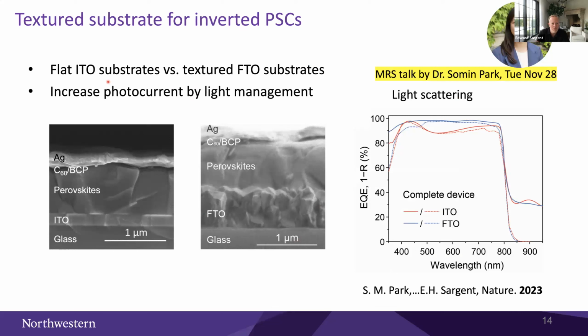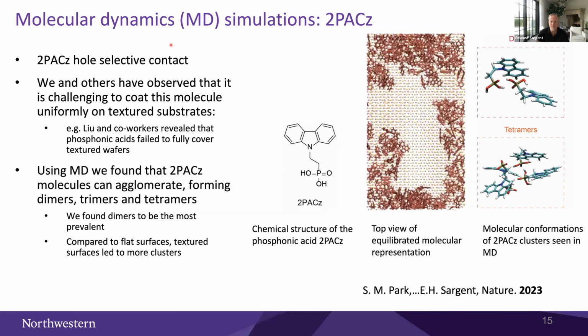the topic that Somin and her colleagues focused in on in particular was the question of whether we could integrate good perovskite active layers with textured FTO. The idea of texturing, of course, is to increase the photocurrent with the aid of light management. Now, the specific challenge that Somin and her collaborators faced was to implement the desired 2PACz hole selective contact, but to coat it successfully and substantially uniformly onto this structured, or textured, substrate.